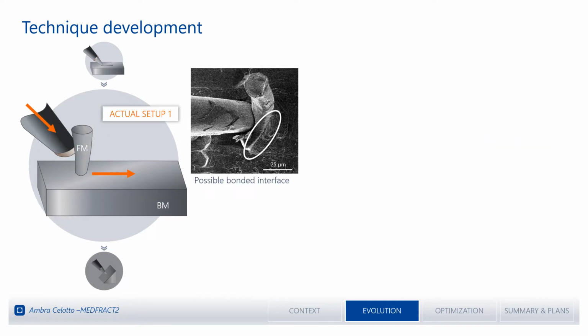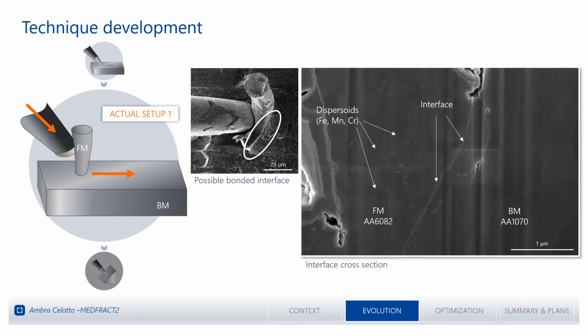And by punching the aluminum tip, the resulting situation revealed a high plastic deformation of both metal pieces in contact, and the possible bonding interface was identified in this white circle. This region was then cross-sectioned, and in the cross-section it was visible that these two metal pieces, which are different in microstructure, were in close contact and separated by a bonded interface. So this procedure looks to be promising, but of course it had to be made systematic and reproducible.